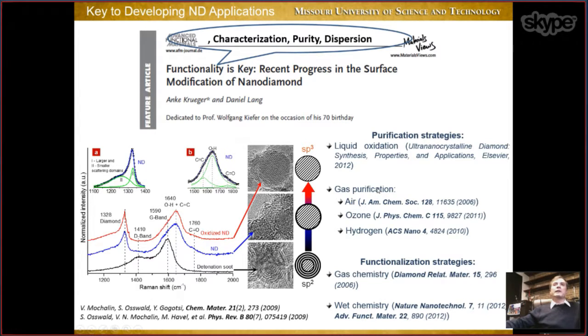But it's not practical because, again, liquid oxidation uses large amounts of very aggressive stuff like nitric acid, chromium oxide, hydrogen peroxide, chloric acid, perchloric acid. So all those are very aggressive and nasty substances to work with. So we developed in 2006 a technique using air for oxidation of non-diamond carbon. But there are also other alternatives. You can use ozone, you can use hydrogen. But again, you need to purify it. You need to use the right technique to purify this material to remove non-diamond carbon.